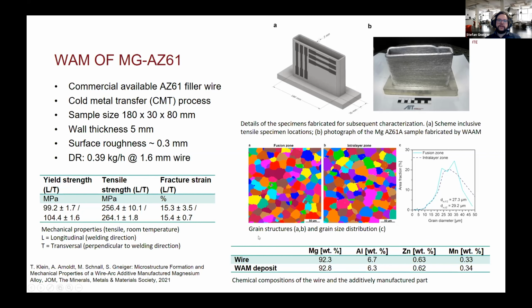We also looked at the chemical composition and compared the chemical composition of the wire with the additive manufactured part, to see if we lose some magnesium due to evaporation. But we have seen that the chemical composition is quite the same. We have a bit higher magnesium values and a bit lower aluminum values in the deposit. So no magnesium is lost.